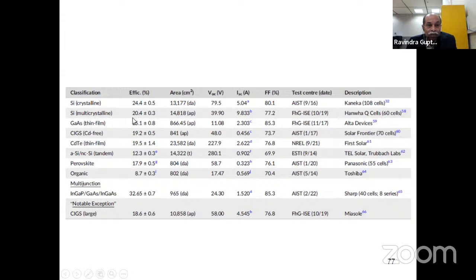For multicrystalline, 20%. For gallium arsenide, this 25%. For the CIGS cadmium-free, it is 19%. Thin film CdTe, 19%. For the tandem cell, 12%. For the perovskite, 17.9%. For the organic solar cell, 8.7%. Okay. For the multi-junction, as I told you earlier, if we have multi semiconductors according to the band gap, then we can collect all wavelengths of the sunlight. Then we can increase the efficiency.